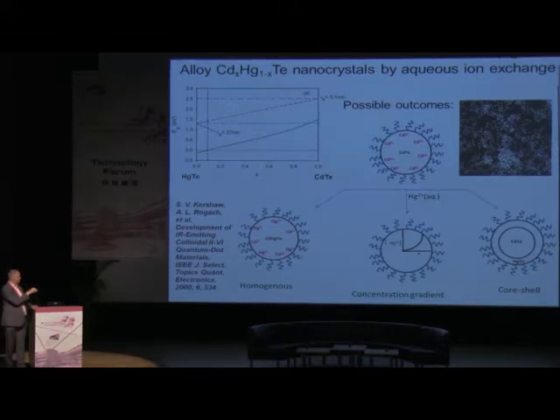There may be a homogeneous alloy, there may be some concentration gradient, starting from the surface, which will be mercury rich, and the inner part may be still cadmium rich, or there may be something we call core shell structure, a well-defined two-phase system, cadmium telluride core and mercury telluride shell. And all this scenario may happen.